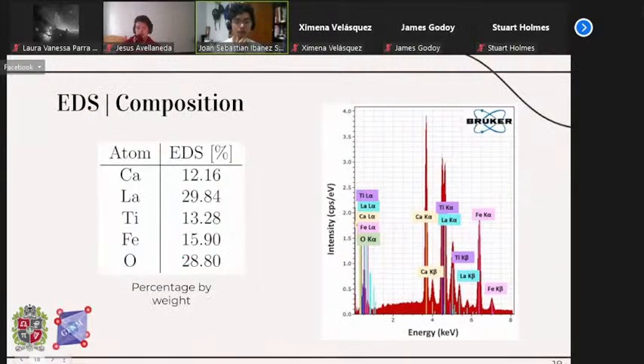That would be the thing about morphology. And now the last thing, we also performed measurements of energy dispersive X-ray spectroscopy to find the composition of our sample. This was made after each of these sintering processes to ensure that we didn't have a lot of contamination. And for the final composition, here in the table you can see the experimental percentage weight composition of our sample.